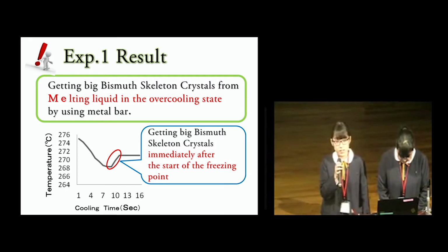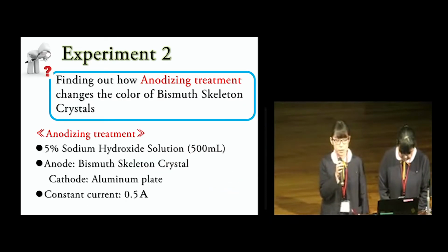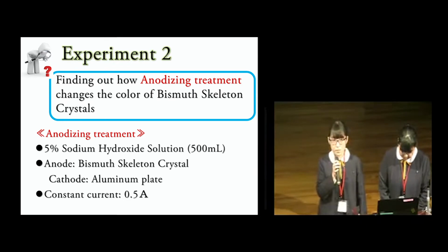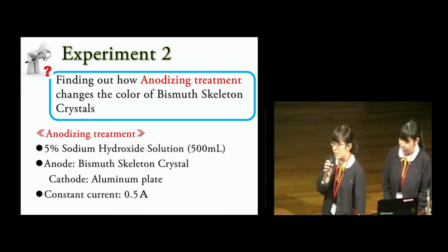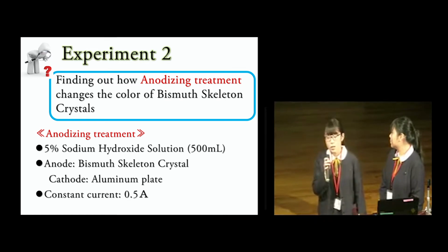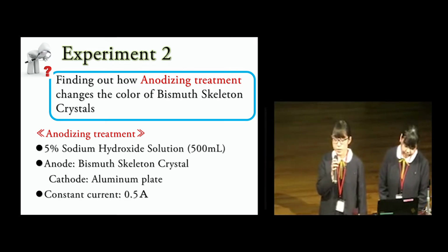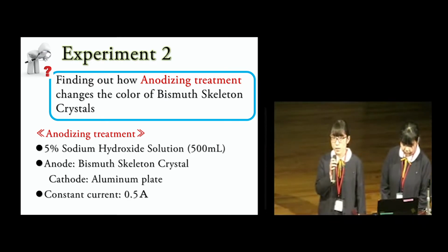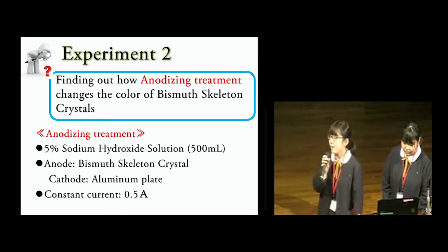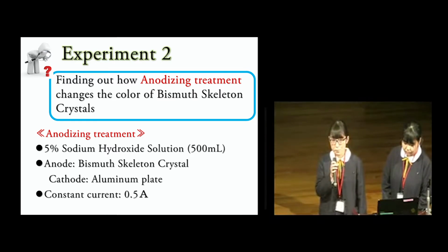Based on the result that all large bismuth crystals obtained in experiment 1 were blue, we thought the bismuth crystals could be oxidized by an oxidation reaction in the electrolysis of an aqueous solution. In this method, 5% sodium hydroxide was used as the aqueous solution. Bismuth crystals were used for the anode electrode, and an inexpensive aluminum plate was used for the cathode electrode. In the experiment, the applied current was kept at 0.5 ampere.